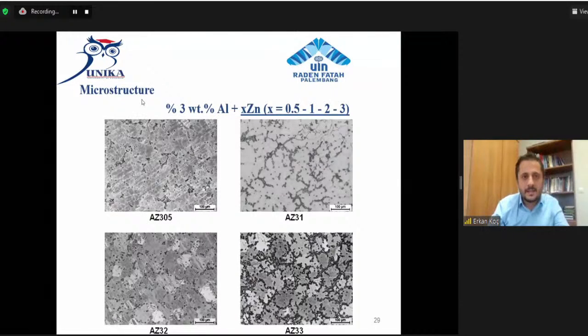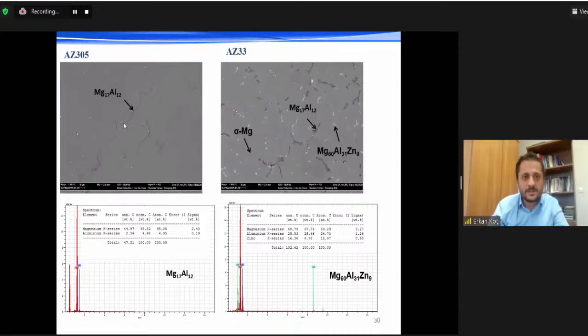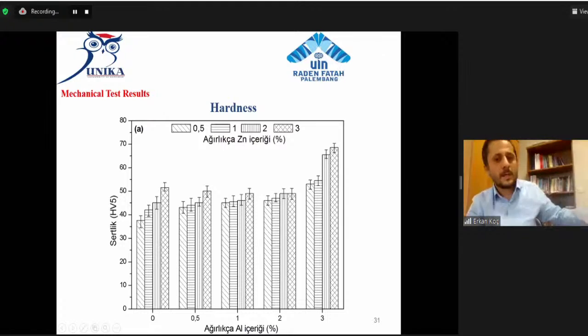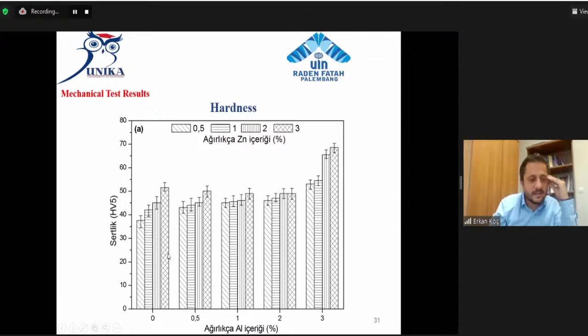You can see here in the SEM microstructure, magnesium 17, aluminum 12 intermetallic phase. Also, another intermetallic phase. And for the hardness test in magnesium zinc alloys, the hardness increases linearly with the increase of zinc amount. Zinc can dissolve up to 2% in magnesium. So the linear hardness increase here is expected to occur from solid solution hardening.